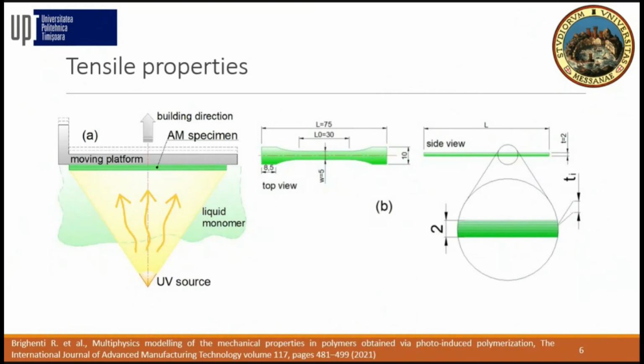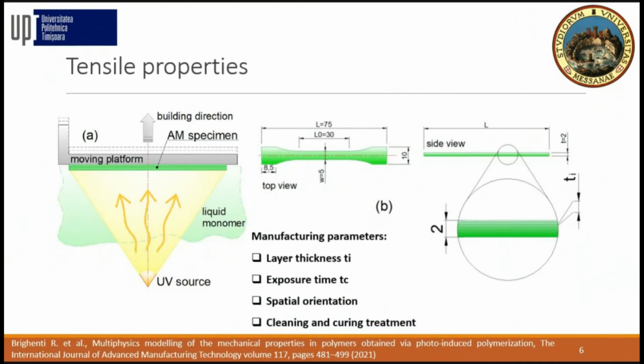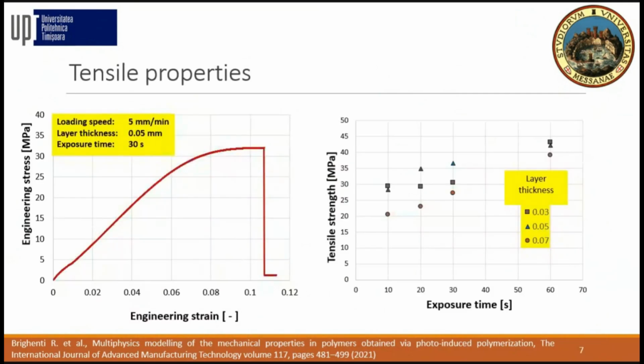Our first results were in tensile, where we played with different manufacturing parameters. We varied layer thickness, exposure time, spatial orientation, cleaning and curing post-treatment. I will show you only some results: the engineering stress-strain curve, and then the tensile strength results versus exposure time and layer thickness. What we can see, and we expect this, is that the tensile strength increases with increasing exposure time. This can cause longer manufacturing time, and also lower layer thickness gives higher tensile strength.